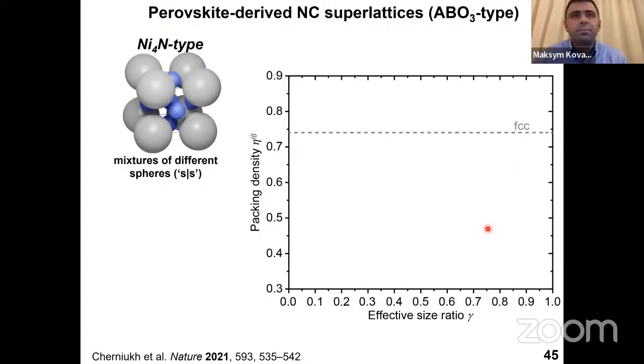And let me show you one very prominent example of such a crystal structure. Look at this mixture of two spheres, which I already told you had never been observed experimentally. So only atoms form this crystal lattice, but nanocrystals, at any size ratio, two spheres never crystallize in this crystal structure. This is the nickel 4N type lattice, which is basically derived from the perovskite lattice, when the facet and the center atom is the same.